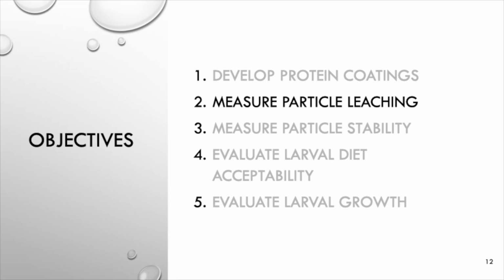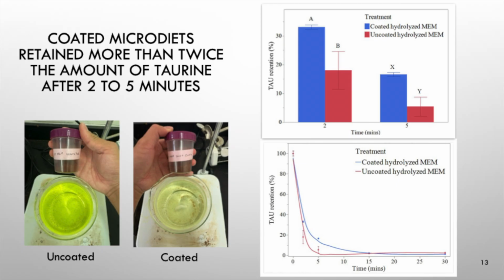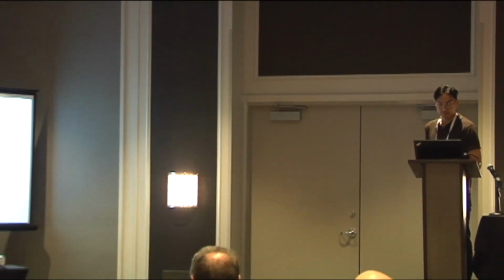Next, we'll be moving on to particle leaching. So we ran both a taurine and sodium fluorescein leaching trial. We used taurine because it is a highly water-soluble, unbound free amino acid shown to improve larval finfish growth. And we used sodium fluorescein because it acts as a suitable proxy for other water-soluble nutrients. In the bottom left images, you can see the leaching of sodium fluorescein of an uncoated microdiet compared to a coated microdiet at 5-minute time points. Both trials showed coated particles significantly reduced leaching, and in particular, the taurine leaching trial showed almost 2 times taurine retention compared to the uncoated diet, and almost 4 times at the 5-minute time point.